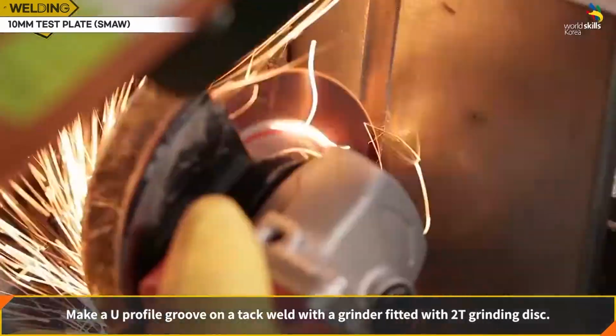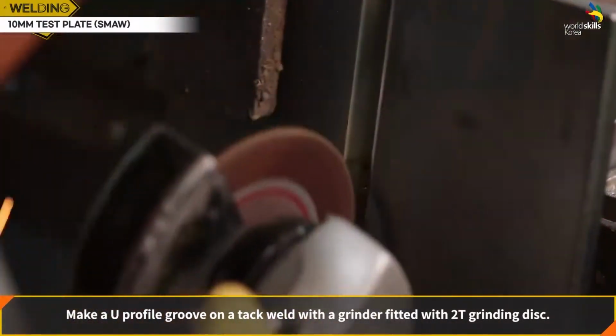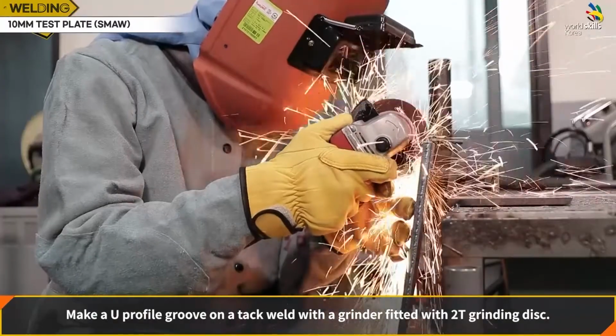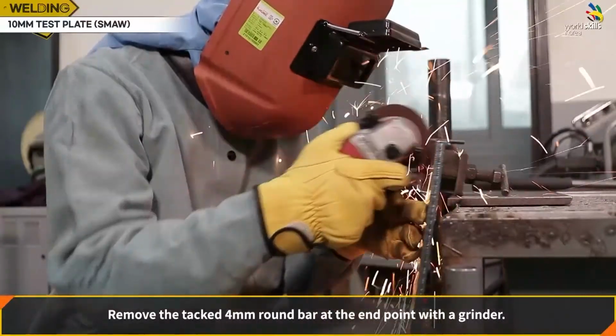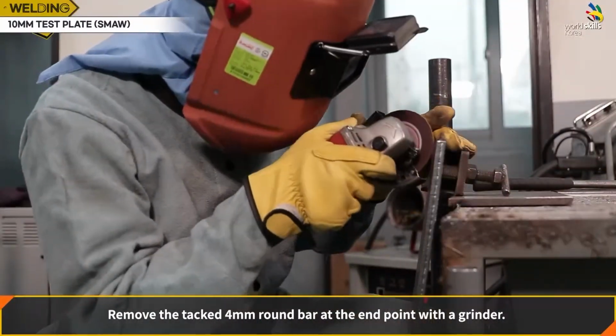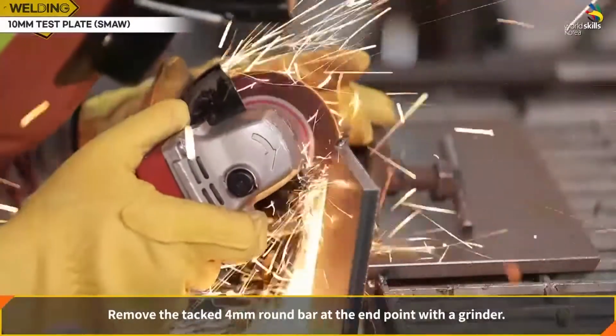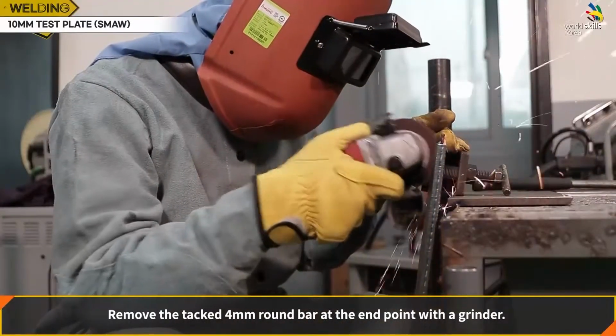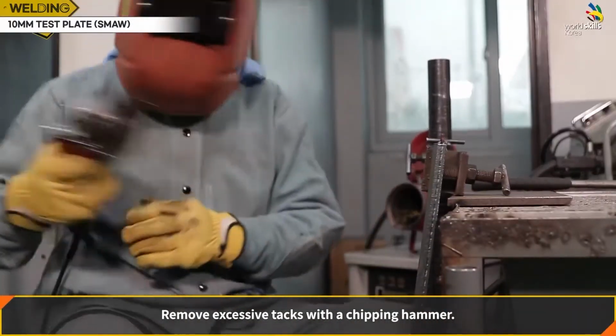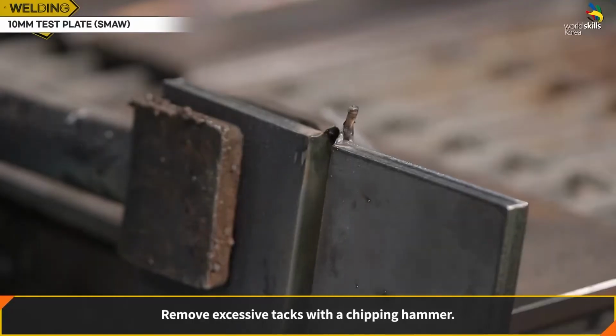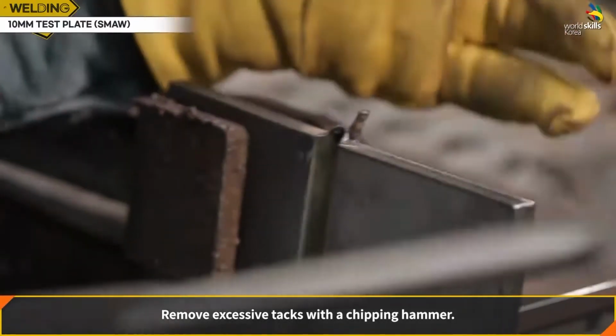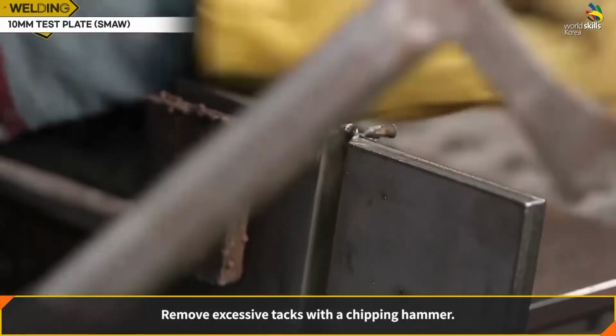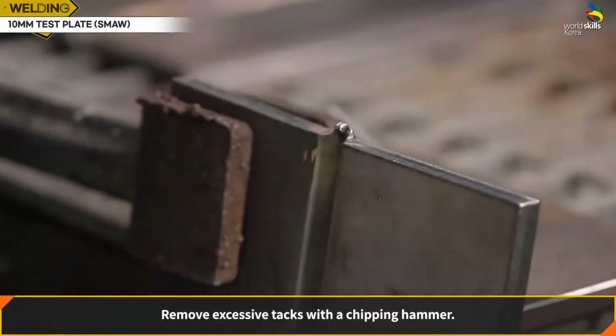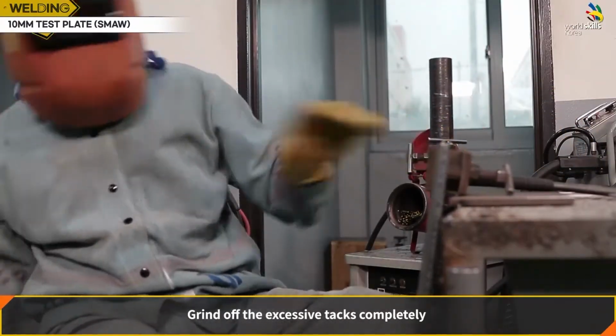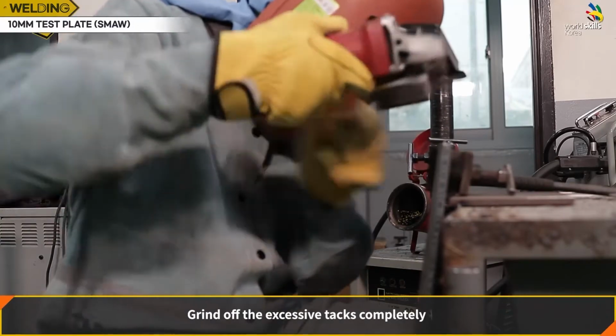Make a U-profile groove on a tack weld with a grinder fitted with a 2T grinding disc. Remove the tacked 4 mm round bar at the end point with a grinder. Remove excessive tacks with a chipping hammer. Grind off the excessive tacks completely.